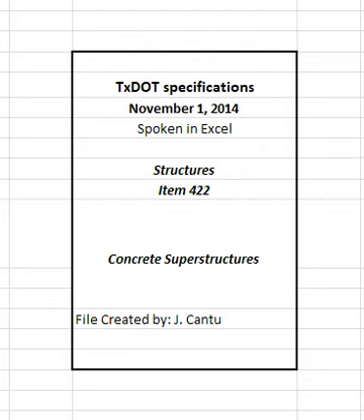4.6.9 Consolidation. Carefully consolidate concrete and flush mortar to the form surfaces with immersion type vibrators. Do not use vibrators that operate by attachment to forms or reinforcement except where approved on steel forms. Vibrate the concrete immediately after deposit. Systematically space points of vibration to ensure complete consolidation and thorough working of the concrete around the reinforcement, embedded fixtures, and into the corners and angles of the forms.